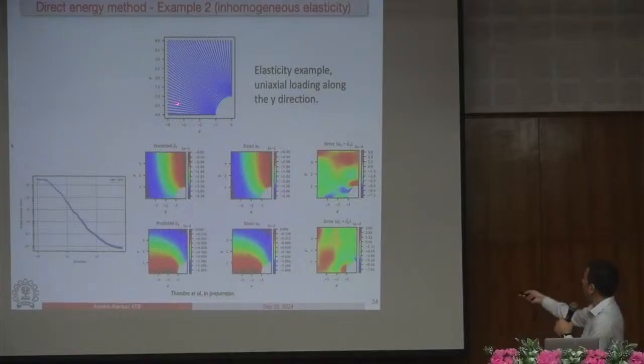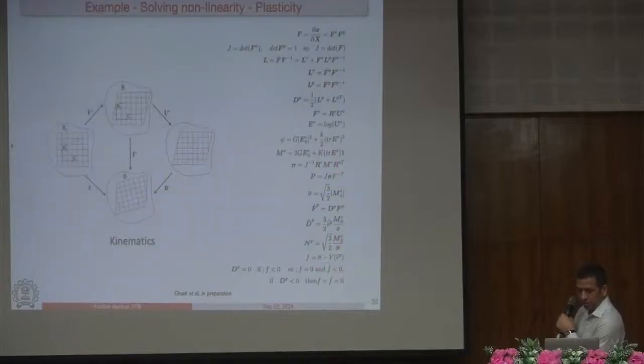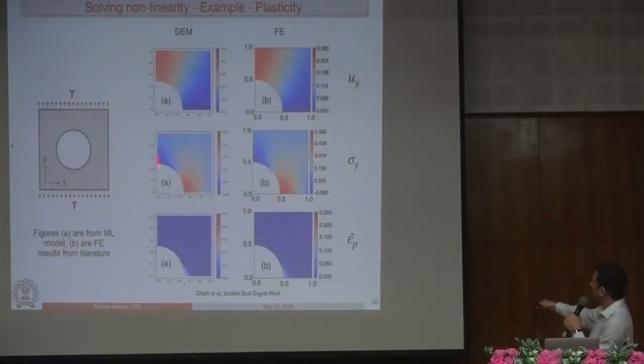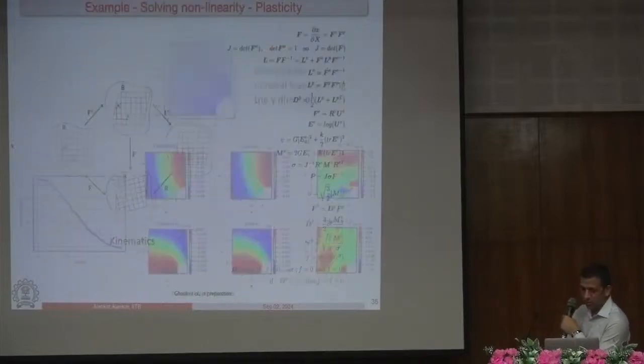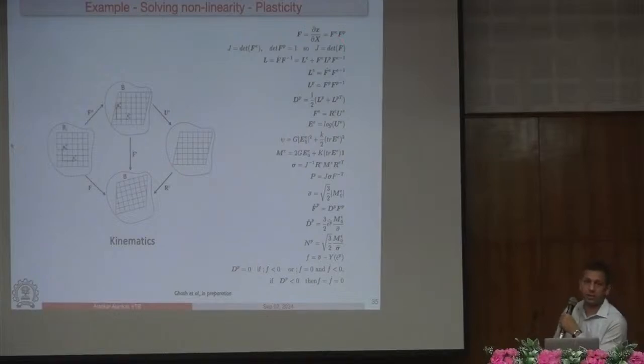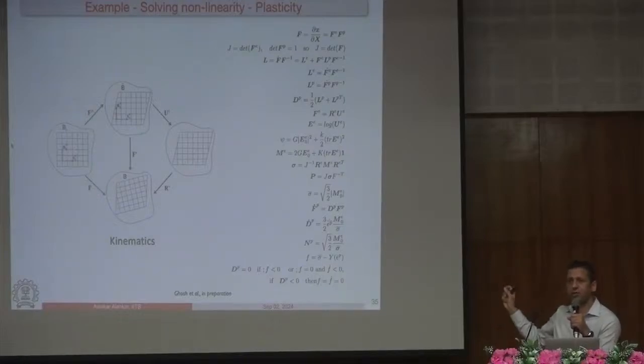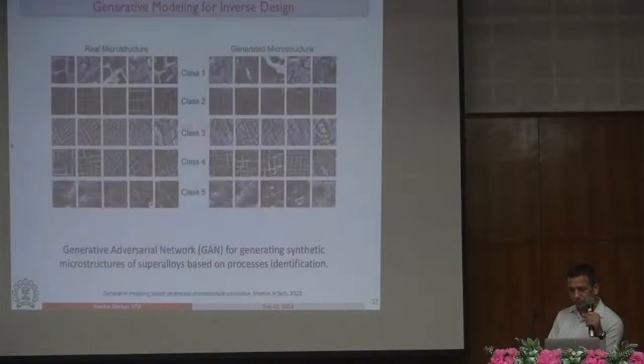So we played with geometry as well and tried to analyze whether the new method is capturing the stress concentration around these non-homogeneities, and it does a very nice job. If you see, we also now have added plasticity to it. So this is the direct energy method, which uses the loss function that I showed you. And here, this is the machine learning solution, and this is the finite element solution, and it is using all the plasticity that we have. This is finite strain plasticity, not the small strain deformation that I showed you earlier. It has huge nonlinearity and is very expensive to run in finite element, right?